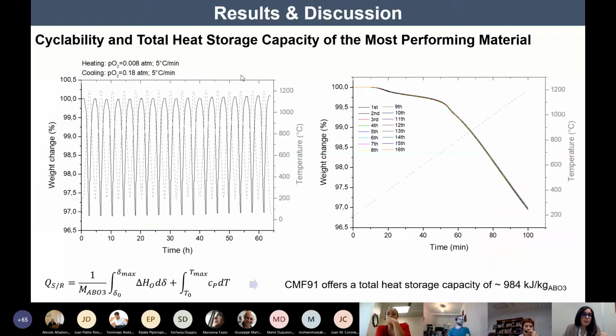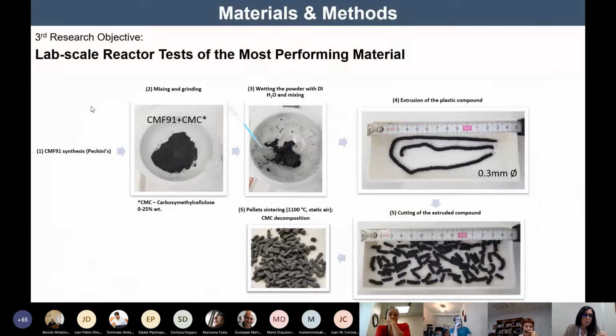We selected this material for testing its cyclability over multiple cycles, and it can be observed how this material is perfectly stable along 16 cycles. We determined the total heat storage capacity considering the two contributions of chemical and sensible heat, which is about 984 kilojoule per kilogram. So it offers a really good heat storage capacity, and we decided to use this material for laboratory scale reactor tests.